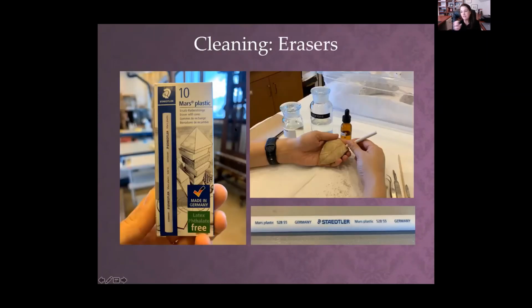But as all the rest of this scholarship was going on, as the provenance was being traced, as everyone was working on their different individual pieces, we started really the treatment of the sculpture. So the first step was to clean the marble pieces. We started first with these Mars plastic erasers. They're really quite wonderful and my favorite treatment to use for marble. People are either horrified or thrilled to learn that what is combined with these erasers is using saliva, which I tend to call personal enzymatic solution because it sounds a lot fancier. But the combination of the two really gives you a controlled cleaning, and it's very, very gentle.